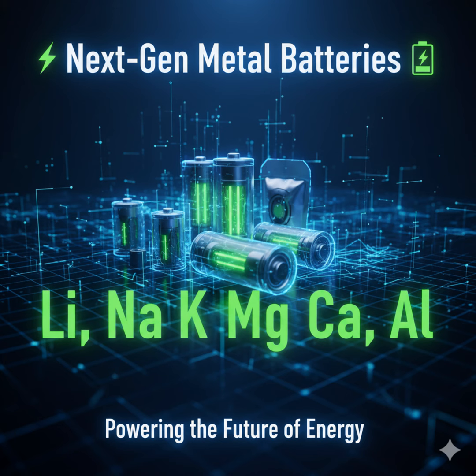That's strategy two, smart electrolyte design. And again, we need opposite approaches. Remember the monovalent problem. Their SEI is too organic and weak, right? The organic mess needs to be tougher. So the strategy is to make their SEI more inorganic, by forcing those electrolyte anions, which normally stay away, to get closer to the Li+ or Na+ ion before the SEI forms.